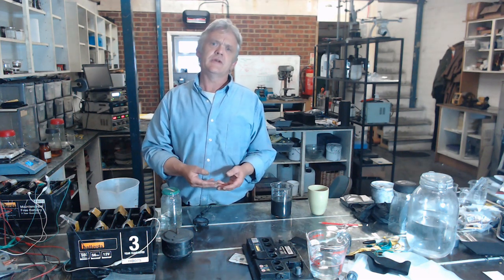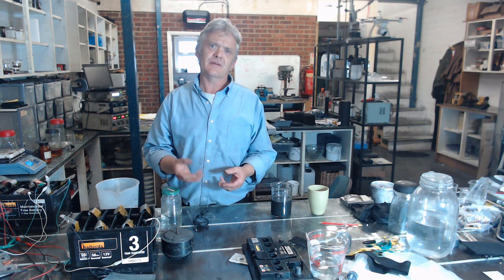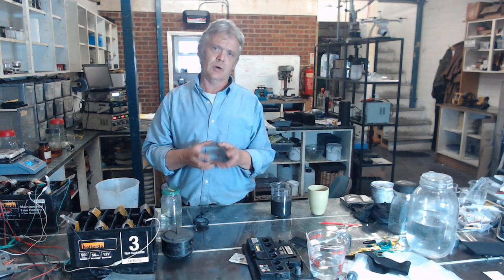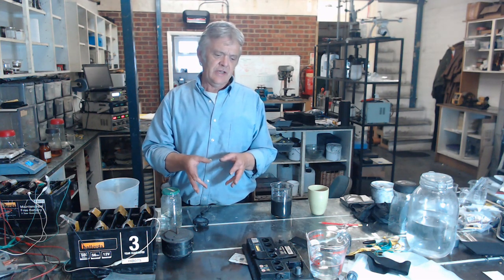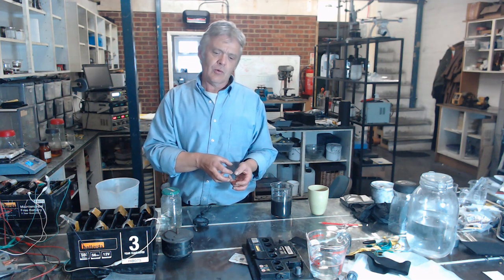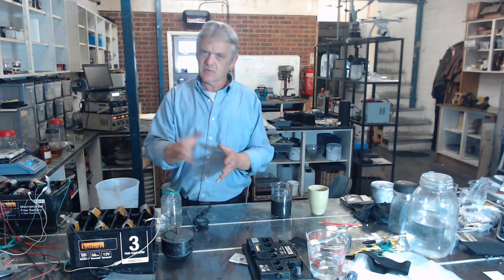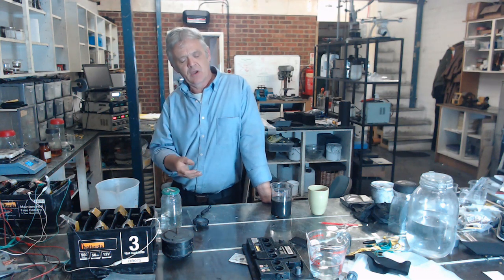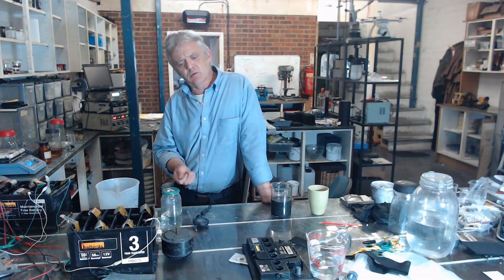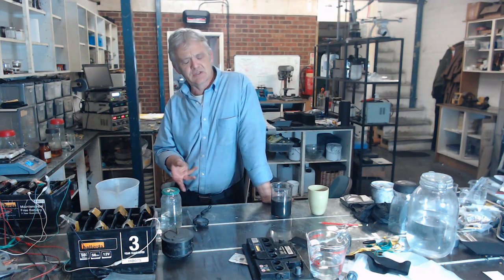Obviously the yield that you get from that is how much graphite you can get out of that original rock that you crushed up. And then the quality is how much is still left in there once you do the carbon content test, which is a really simple test. It's called loss on ignition. Graphite will actually begin to burn off somewhere between 400 and 600 in an oxidizing atmosphere.